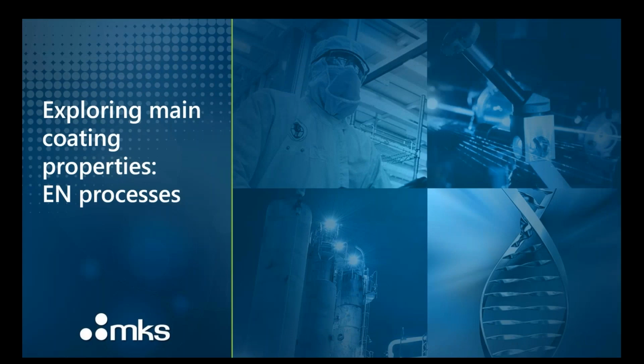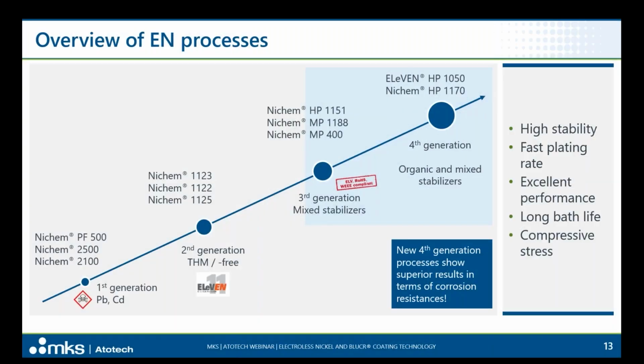Let's have a look at the main coating properties and at the electroless nickel processes at Atotech. First, I would like to give you an overview of the development of the electroless nickel processes, which is actually based on the evolution of the electroless nickel stabilizers used in these processes. So the first generation of the electroless nickel processes was stabilized by lead and cadmium, but as these two toxic heavy metals became banned by the regulations, we were looking for new stabilizers.